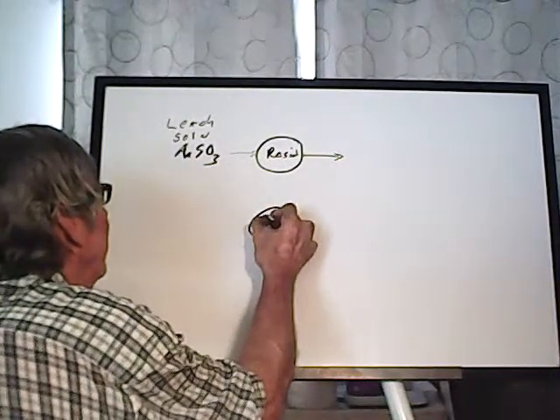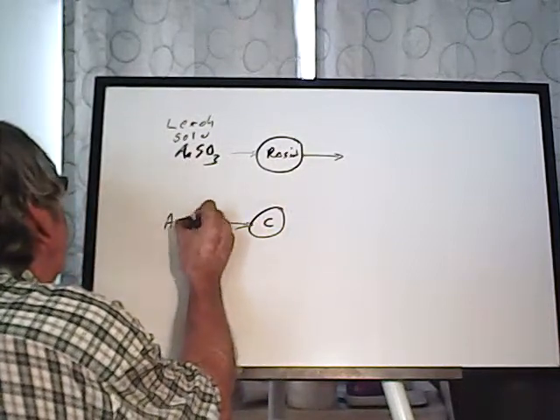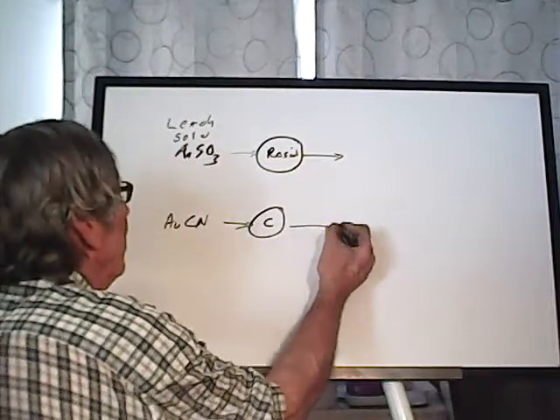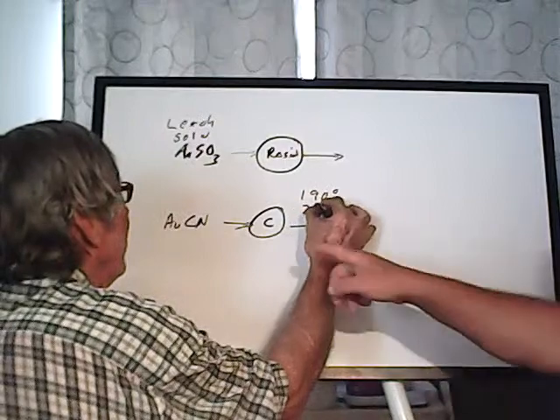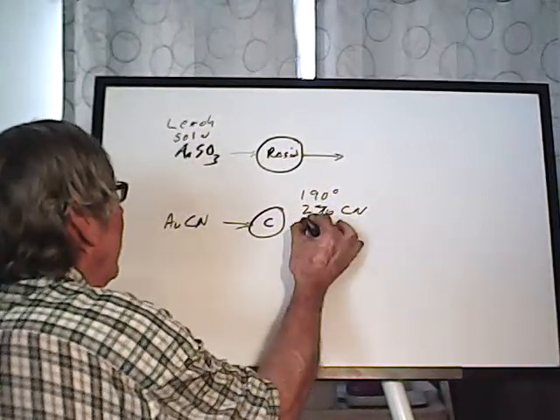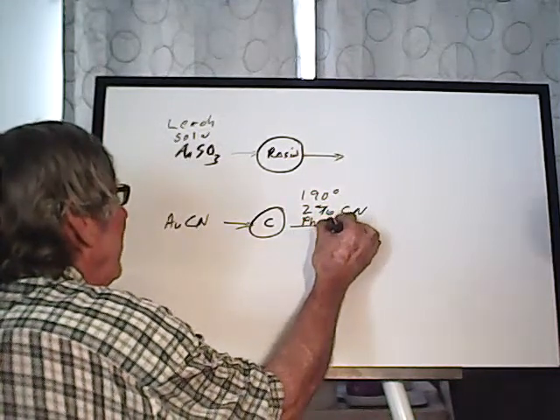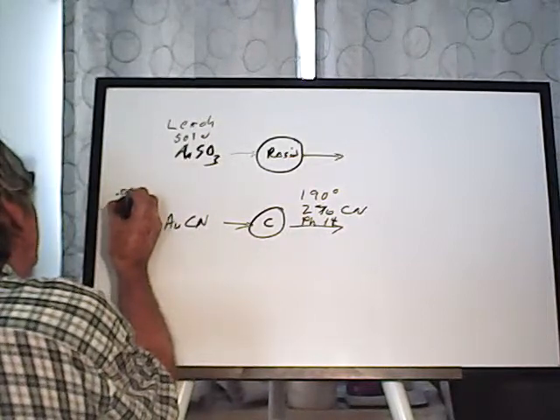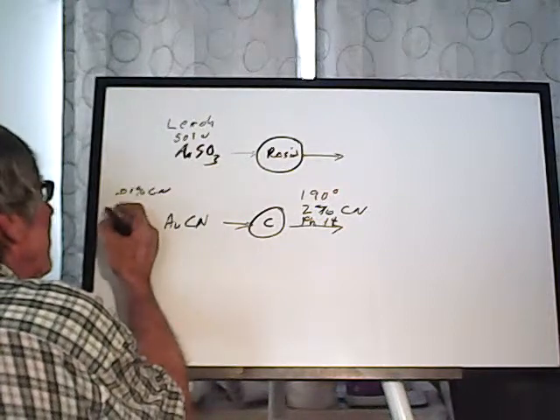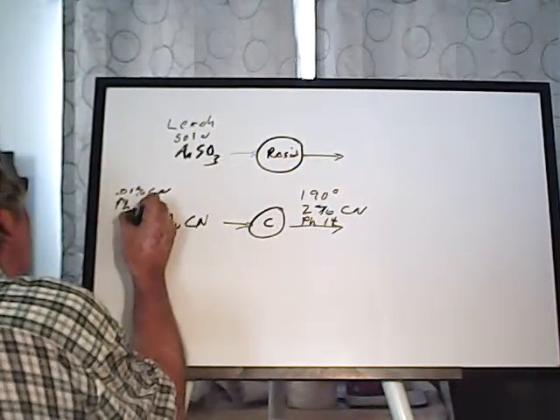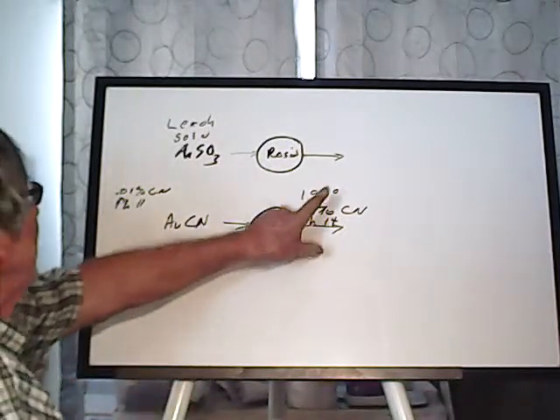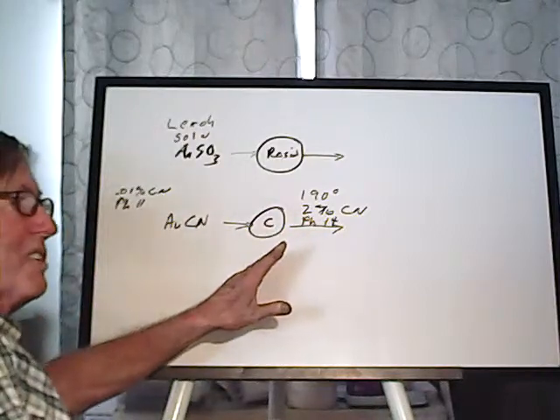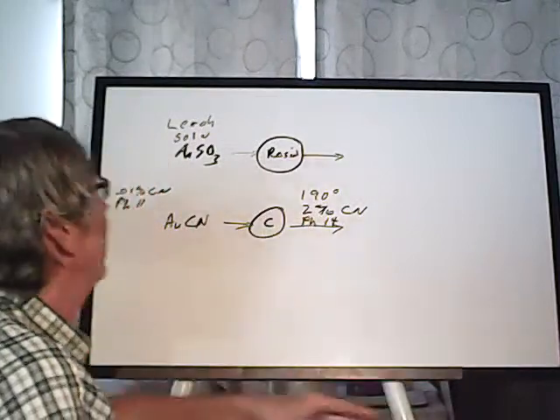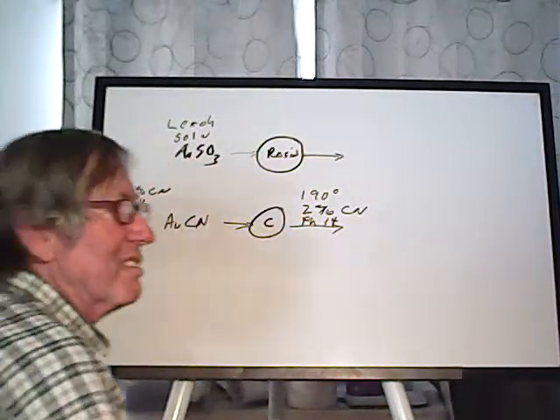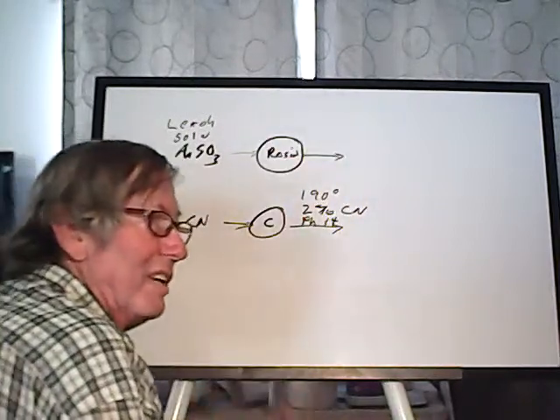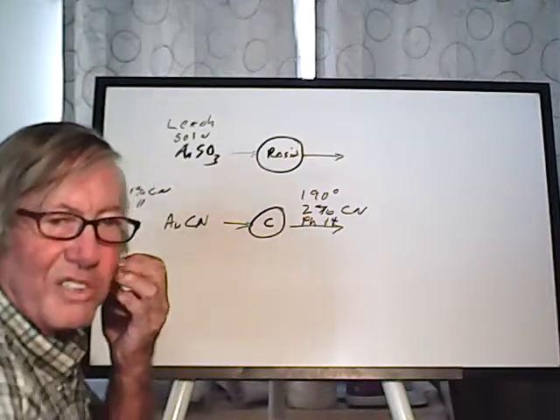In the case of carbon, what we used to do was 190 degrees, 2% CN, and a pH of 14. This was 0.01% CN, ambient temperature, and a pH of 11. So by changing these conditions, the equilibrium changes from going into the carbon to coming out of the carbon. Right. And that's what we're going to do with the resin too. What these exact conditions are, we don't know yet, but there is some information in the literature.